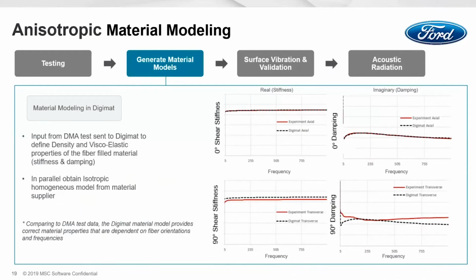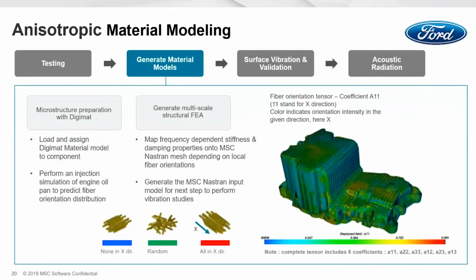graph. So 0 degree measurements, both shear stiffness and the delta at 0 degree are perfectly captured. And then at 90 degree measurements, the gap on shear stiffness is less than 5%, and the gap on the delta is 0.0003 here. So next, we look at the anisotropic material modeling. Here, we perform an injection simulation model of the engine oil pan to predict the fiber orientation distribution inside Digimat. So fiber orientation tensor coefficient is shown as A11.